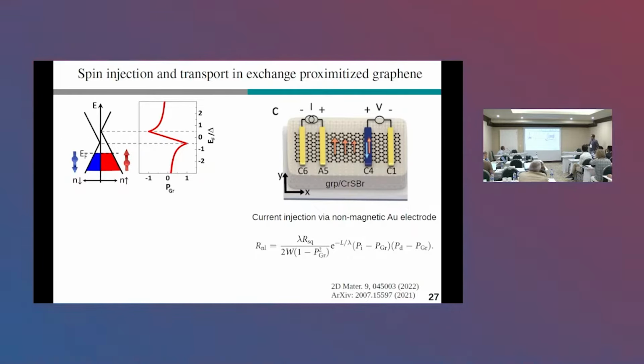And this non-local resistance signal depends on the injector, the graphene, and the detector polarization. And in this case, they were using non-magnetic gold electrodes, which means that the injector polarization is 0. And this also means that we have only 2 contributions left, which is the polarization of graphene times itself, this product, which simply gives you a spin-dependent background. And then this remaining product, P graphene and the detector one. So the detector is cobalt.